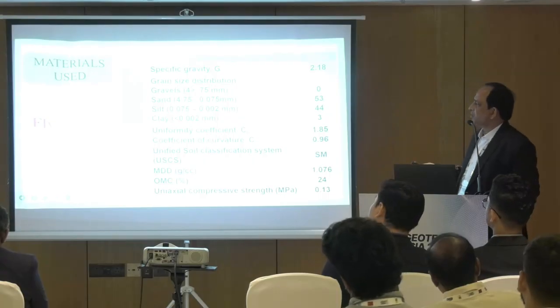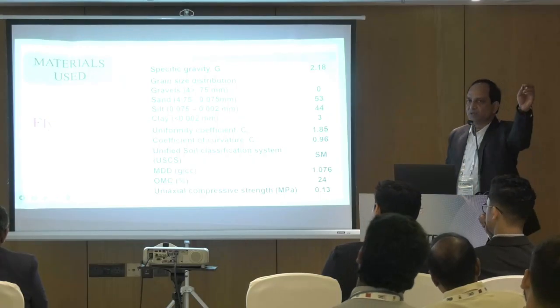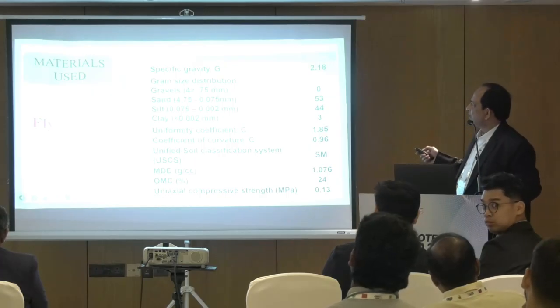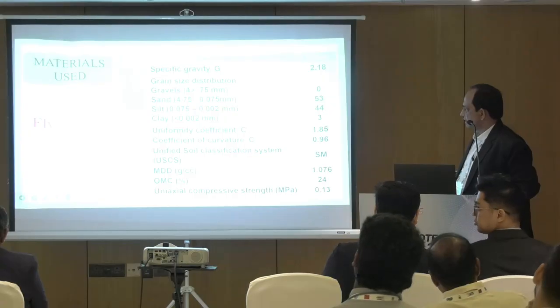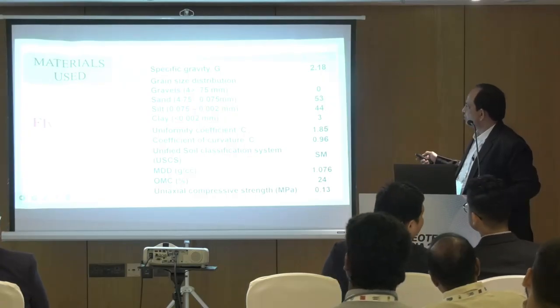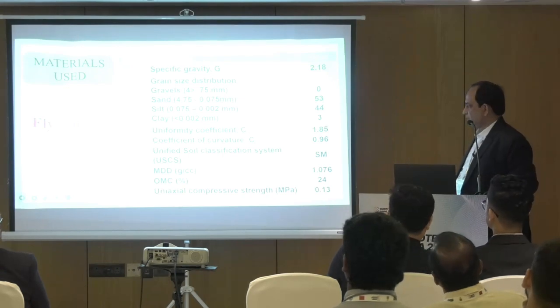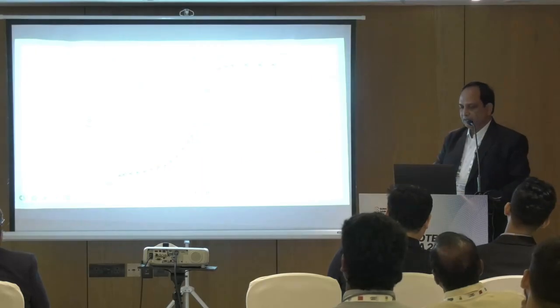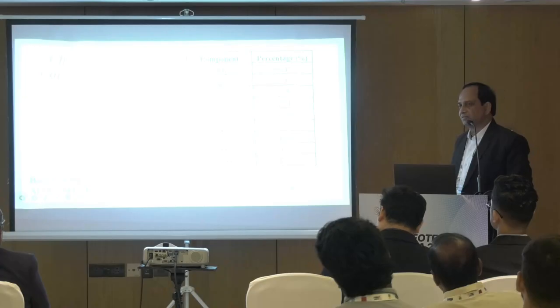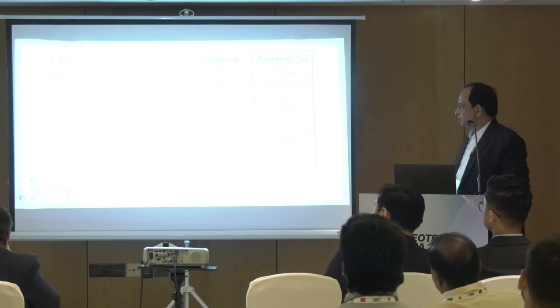Friends, this is the ash we got from NTPC Ramagundam, which is one of the popular plants in South India. With a specific gravity of 2.18, it is a silty sand with sand and silt in almost equal amounts, and with a very low UCS value of 0.13 MPa. And this is the particle size distribution. The basic chemical composition turns out to be class F fly ash because of its low concentration of calcium oxide and huge amount of alumina, silica, and ferrous oxides. So it turns out to be class F based on this chemical composition.